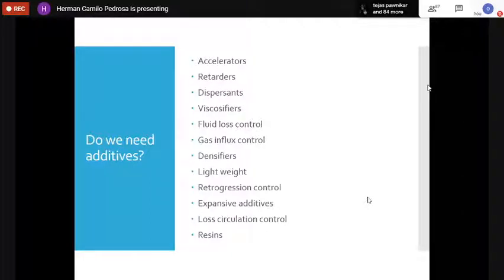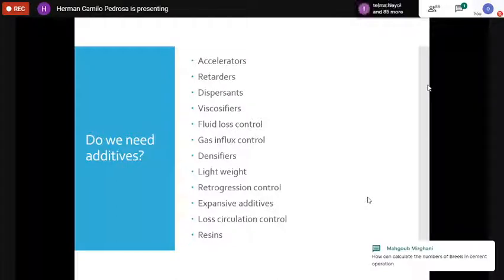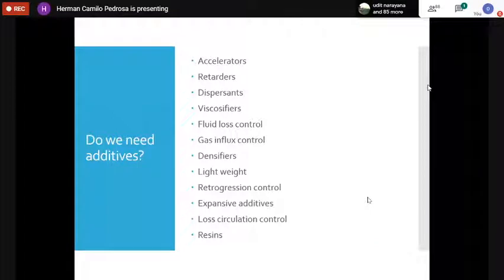And also we have the retarders, which are pretty much the opposite. If we have a cementing operation that will take 10 hours, and we have a cement that, because of the heat and the properties, will set in just 4 hours, we will need to put in some retarders to keep the cement fluid for a longer time.